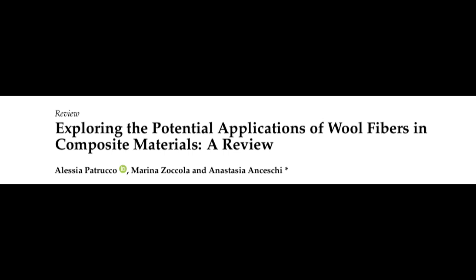Okay, so challenges exist, but the review does highlight successes, right? Where has it worked well? Yes, definitely. In polyester matrices, for instance, some research surprisingly found that adding more wool fiber actually increased tensile strength and hardness up to an optimum around 50% wool by weight. 50%. That's a lot. It is. And these polyester wool composites also showed decent mechanical properties overall and good impact resistance.